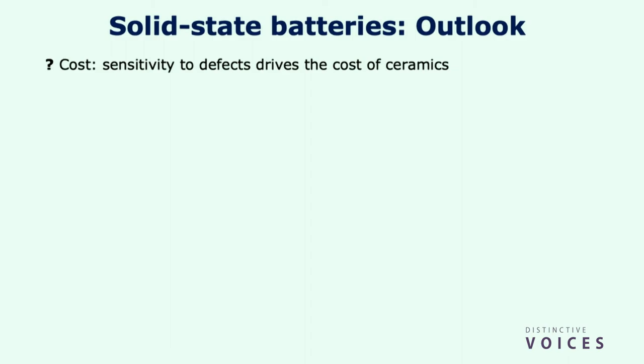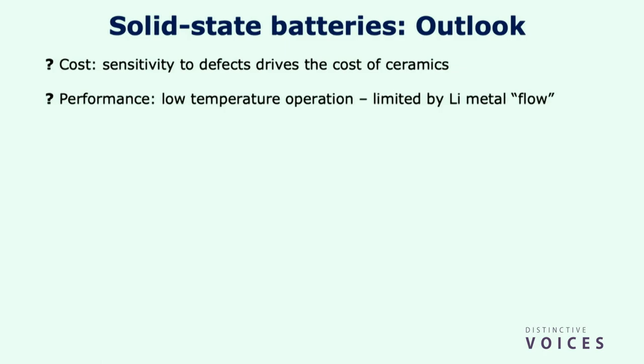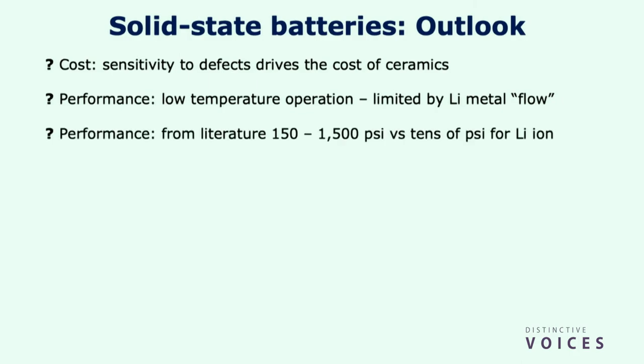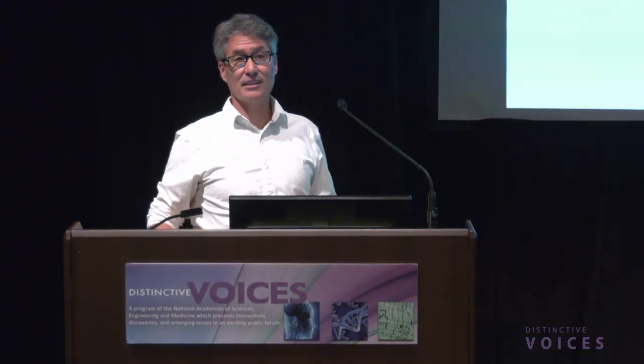If they're ceramics, ceramics are expensive because their performance is very sensitive to defects, so manufacturing is expensive. Performance, low temperature operation is somewhat of an issue because if you're using lithium metal, it doesn't flow so well at lower temperatures. Pressure is a big one. With these solid state batteries, there's no liquid interface that can follow the solids as they grow and contract. So one has to apply pressure. In literature, what we see is a lot of pressure, between 150 to 1500 PSI. 1500 PSI, if you go to get a soda, the CO2 tanks, those are over 1000 PSI. That's a lot of pressure.